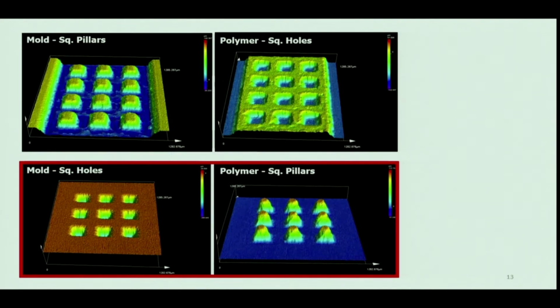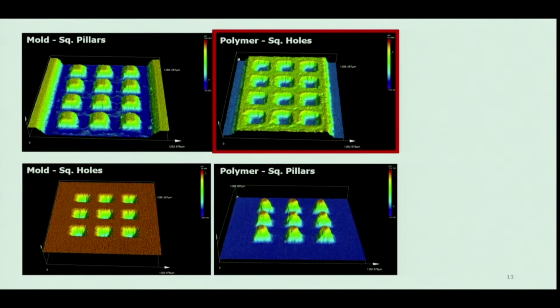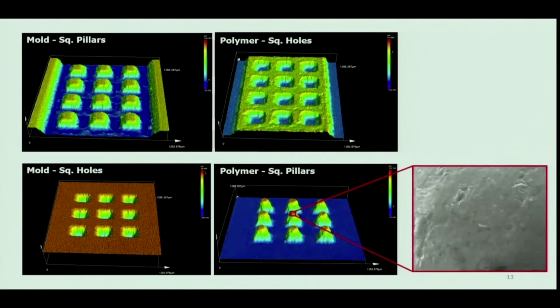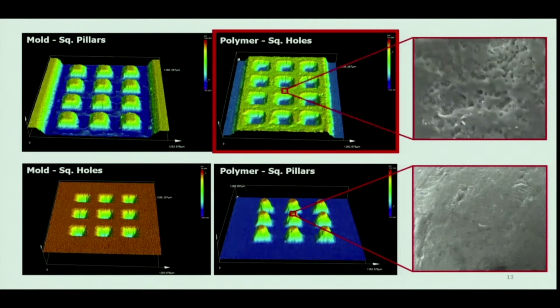The bottom images are the inverse: the square holes placed in the mold and square pillars molded in the polymer. And so far, the square holes replicas presented the best hierarchical structures replicas. And in the zoomed image from the top of a square pillar, you can see that it is flat, without the nanostructures needed to create the hierarchical structures. However, on top of square holes, you can see the replicated nanostructures on top of the microstructures as desired.